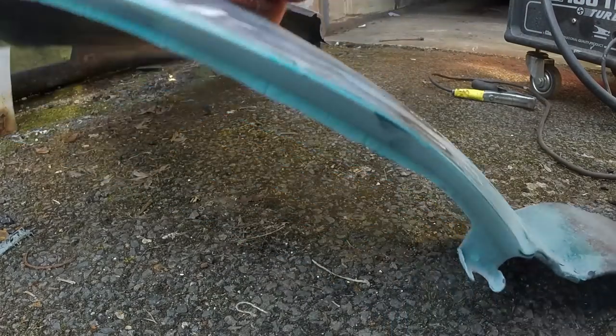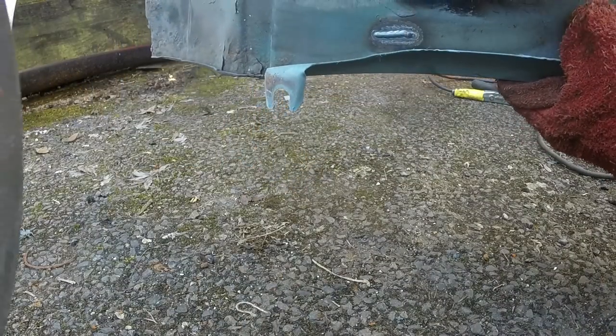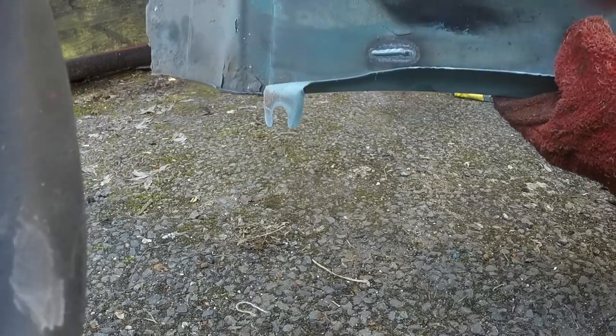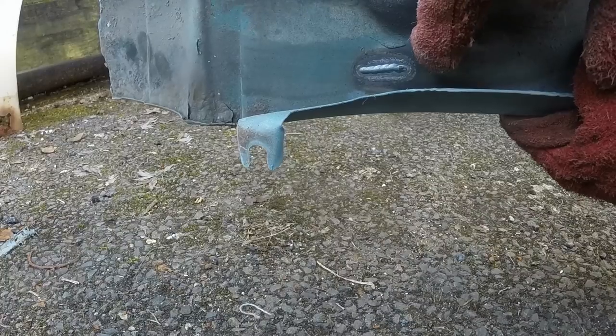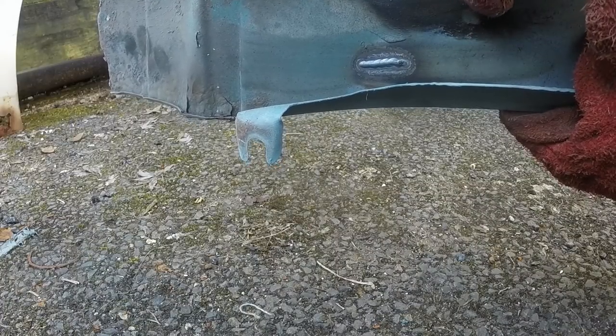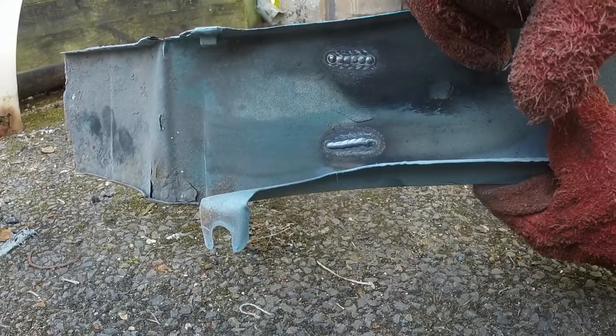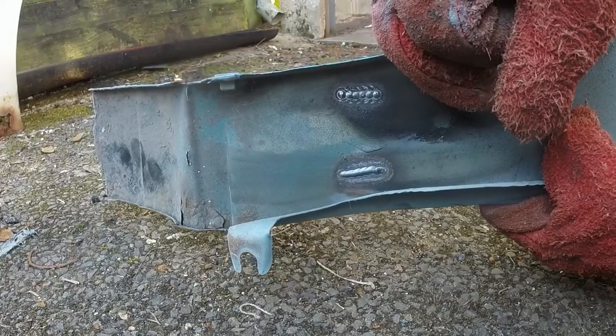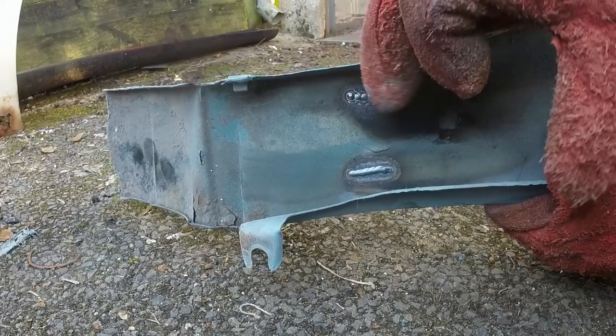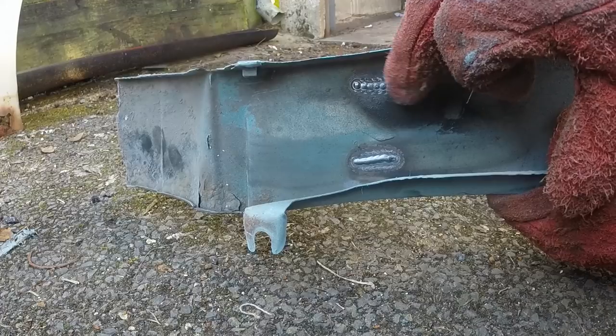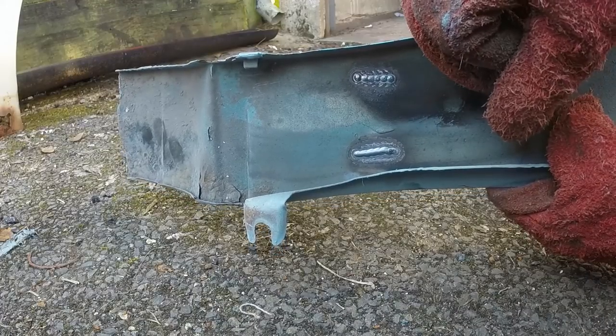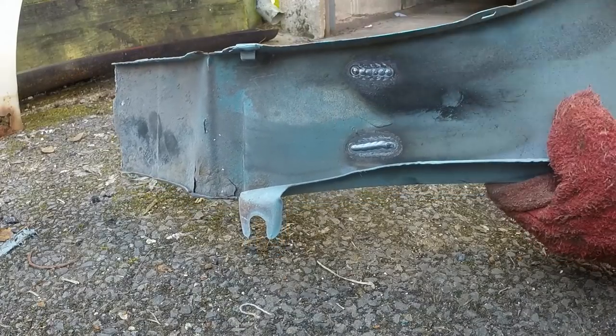If we turn the panel over, you'll see how the penetration compares. So that obviously is our seam, and that is our row of stitches. You actually end up getting about the same amount of penetration, which is quite reassuring, because you know that if you've done this on your car, regardless of whether you seamed it or did a little row of little stitches like that, it's penetrated through the full thickness of the metal.